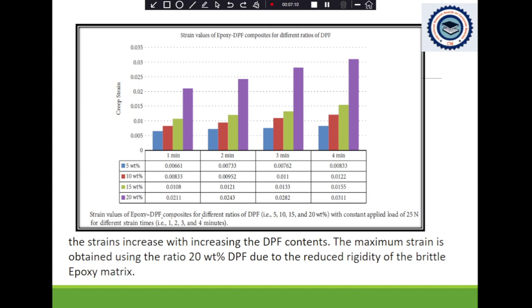About this slide, we are now talking about the creep strain, and we can see the increase with time: 1 minute, 2 minutes, 3 minutes, 4 minutes. The blue one is for 5 weight percent of fiber, the red color represents 10 weight percent, and green and purple also show the weight ratios of the fiber. From this figure, we can see that the 20 weight ratio has the maximum creep strain, obtained using 20% of date palm fiber, due to the reduced rigidity of the brittle epoxy matrix.